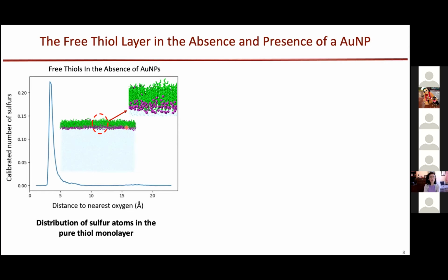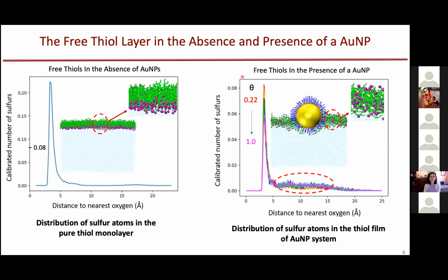This is consistent with X-ray measurement. However, if you put gold nanoparticles in there, the free thiols become disordered, and as you increase the coverage, they become more and more disordered. You can see the sulfur atoms distributed all over the place, normal to the interface, showing that the interactions between the free thiols and the bonded thiols are quite strong.